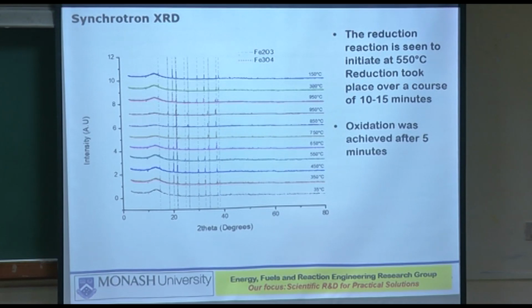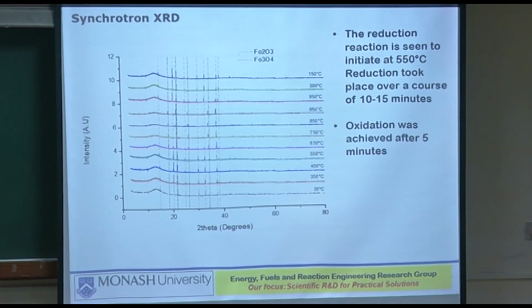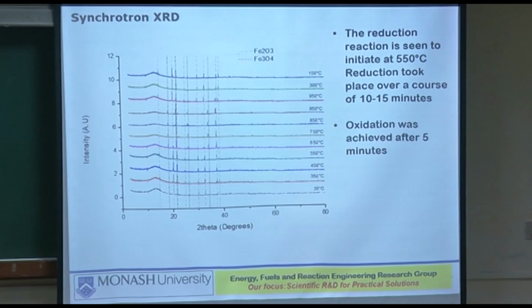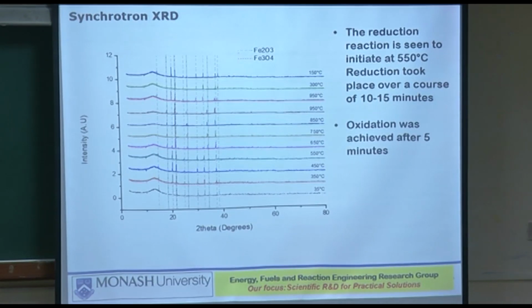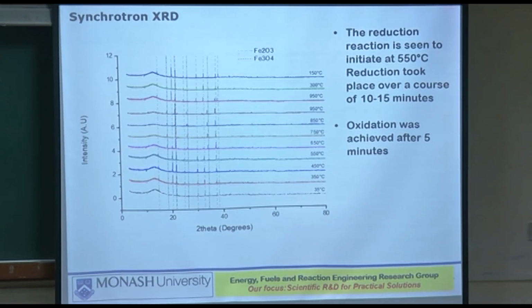At what temperature is it changing from Fe2O3 to FeO to Fe3O4 to Fe0? Because when it has reached the Fe0, if you can detect that temperature, then you know that that is the highest temperature that you would like to have in the fuel reactor for those particles. So this is a beautiful technique to identify that, because it's in situ. It is not ex situ.